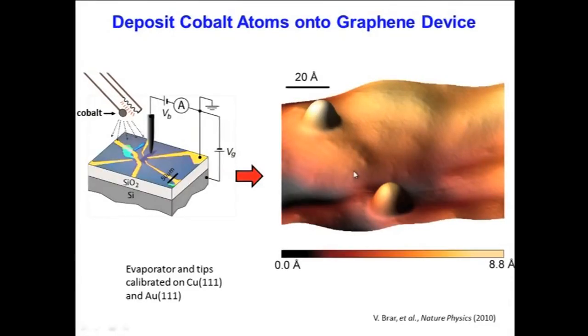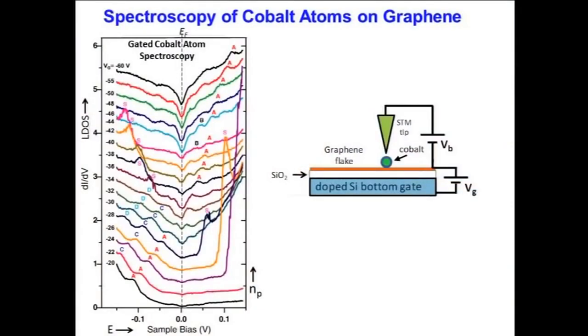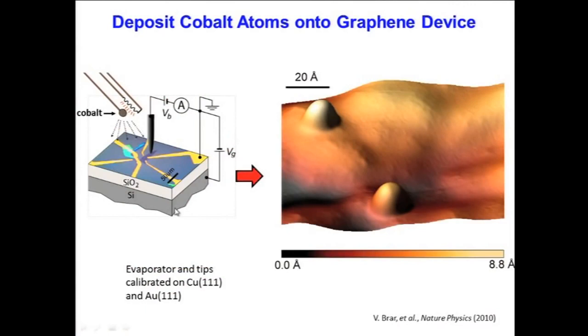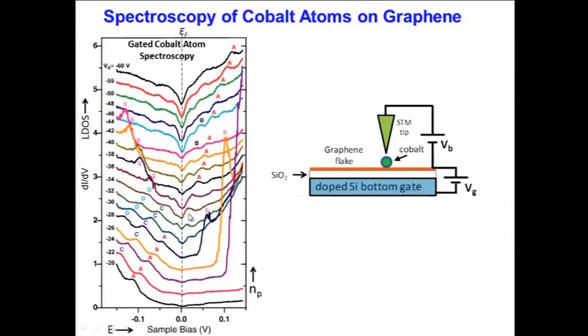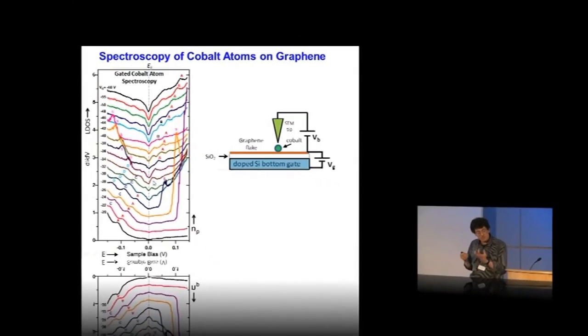We put our STM tip on top of those cobalt atoms so that we could measure their electronic structure, and here I show you that. This is the electronic structure of a single cobalt atom sitting on top of a gated graphene device. This is dI/dV as a function of sample bias. Here's zero, the Fermi energy. Each of these curves is for a p-doped sample, increasingly p-doped as we go up. You can see there are a lot of features and resonances. This is all due to the electronic structure of that atom sitting on the graphene.